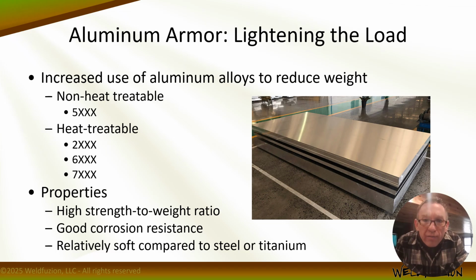Ground combat vehicles often employ 5000 series aluminum for armor applications. It's non-heat treatable. Although 2000, 6000, and 7000 alloys may also be used, with only the 5000 and 6000 alloys being readily weldable using traditional fusion arc processes like gas metal arc welding or gas tungsten arc welding. 2000 and 7000 series often require solid state welding processes such as friction or friction stir, so that we don't experience cracking that can happen because those alloys are highly prone to cracking.